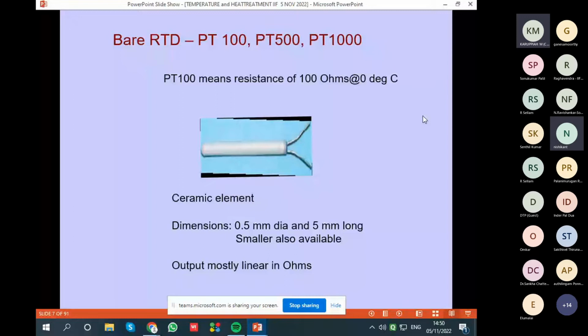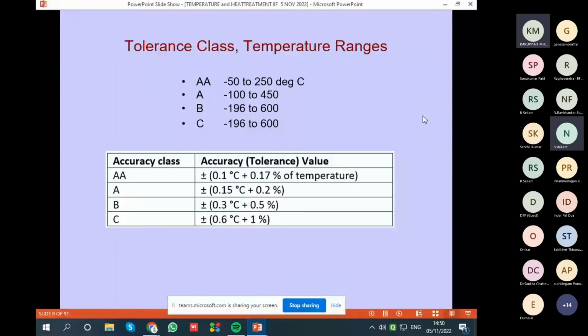Just to tell you, the accuracy you can achieve is 0.1 degree, 0.15 degree. All these accuracies are achievable. Of course, the temperature range is lower, up to 600 degrees centigrade. But if you want to use them in your ore plant or sand making plant, these are suggested because you can measure it very correctly.